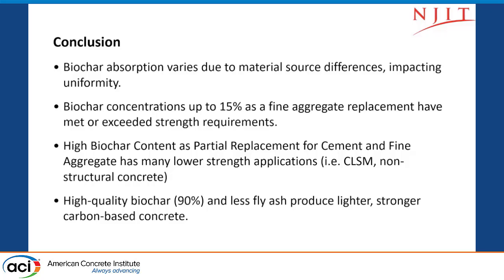So the conclusion of this study is that the biochar absorption varies due to material source differences, as we showed. And actually I received last week a biochar sample. They said that it has minimum 90% carbon, so the factors are endless. So I would like to try this 90% biochar. I don't know how much it costs, I think it might be higher, but they said that your biochar at 60% is very low, so try the 90%. So we are still open for all the factors and all suggestions.